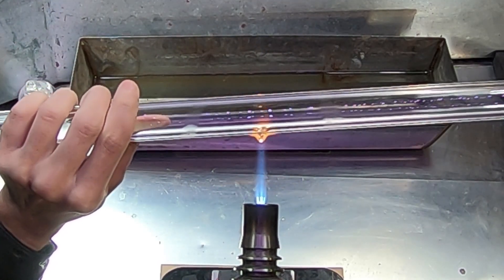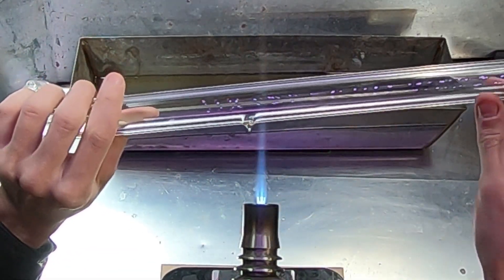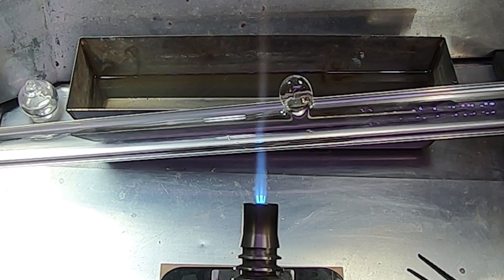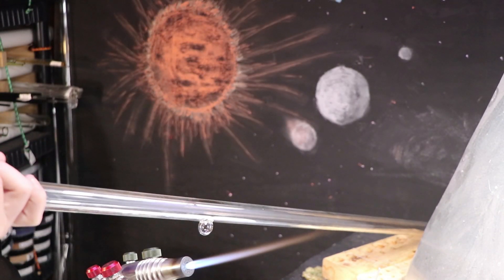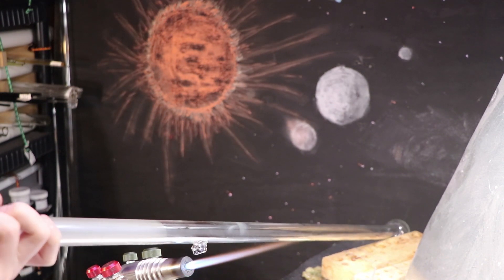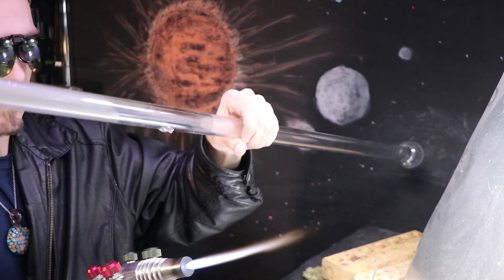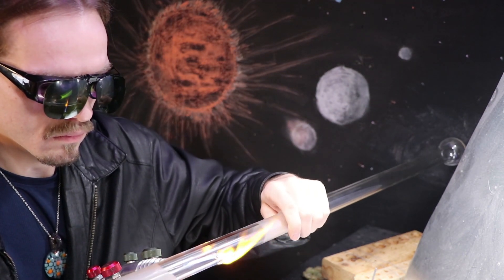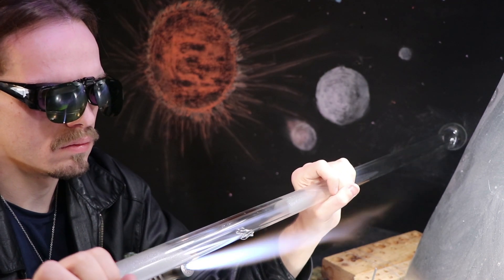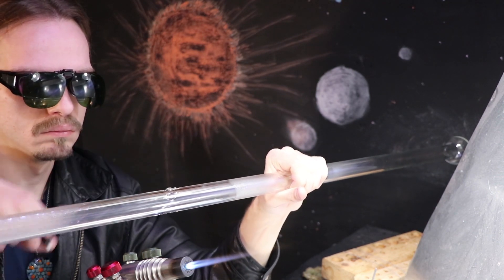I'm just heating up a small area and pulling out a little bit of glass to thin up the wall, so it'll blow out very easily. I'll blow into it to puff out a very thin bubble, which will melt open very easily in the flame. I'll just brush it in the flame and it tears right open. Then that remaining thin glass will melt back very quickly. I'll heat it up and use my mini jacks to shape up a square for the switch. I don't want to open it up too much as it might jeopardize the stability of the center. I'll brush it on the very outskirts of the flame to bring it down much slower so that it doesn't shock the piece as it cools.